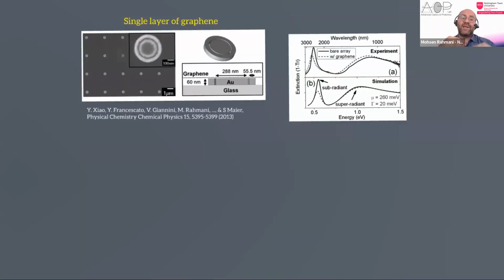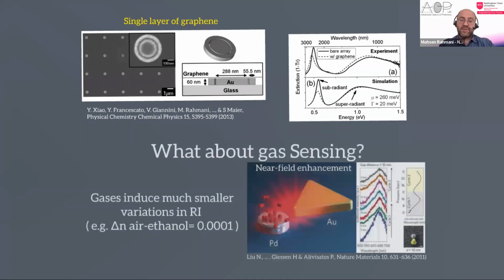And even more, not 2 to 7 nanometers, even if you go to sub-nanometer or single layer scales, metallic nanoparticles or plasmonics can still be used for sensing. This is another paper in which I was again involved in those years. Here we showed that with the right design, we can even detect the existence of one single layer of graphene, which is around 3 to 4 angstroms in thickness. But still, the near field enhancements are strong enough and sensitive enough that we can use them to detect such a thin layer of material next to our nanostructures.